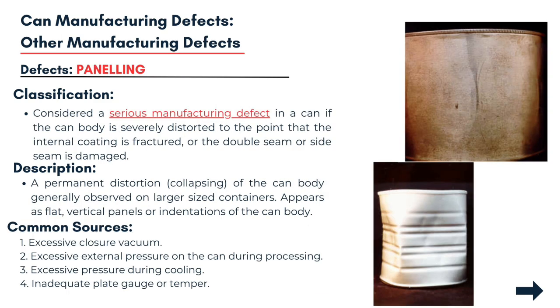Paneling is also another manufacturing defect. It is identified as a serious manufacturing defect typically observed in larger size cans. It is characterized by a permanent distortion or collapsing of the can body, appearing as flat, vertical panels or indentations as what you see in the picture. This severe deformation of the can body is considered serious if it reaches a point where the internal coating is fractured or the double seam or side seam is damaged, compromising the can's integrity.